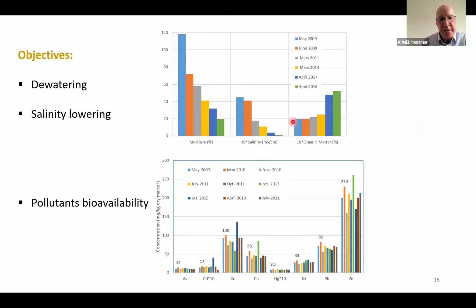The objectives of the land deposit were dewatering and salinity lowering. So if we see in this diagram for this first deposit between 2009 and 2018, the moisture decreased from 120 to almost 20%, and the salinity also decreased from 40 to 4, 10 times, but the organic matter increases.